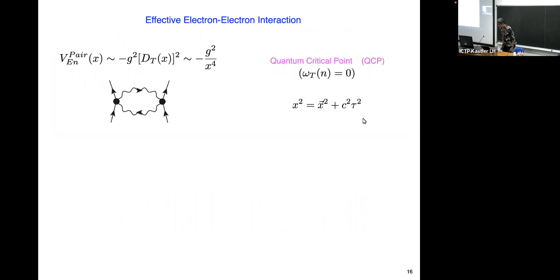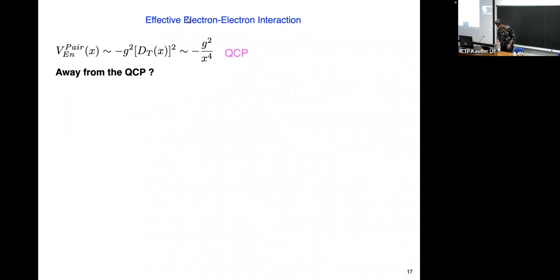So what's our effective electron-electron interaction? Our effective electron-electron interaction at the quantum critical point goes as 1/x^4. Here, omega goes like q. The phonon propagator goes as 1/q^2. So here it goes as 1/x^2, and 1/x^4 because we have two phonon propagators. Here I'm taking x to be a four-vector, so I'm including space and time. At the quantum critical point, I have a 1/x^4 behavior.